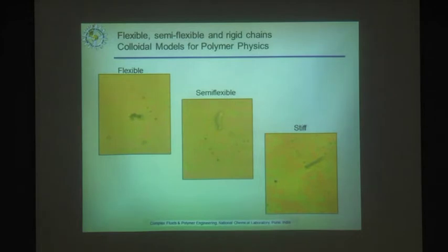The other thing that is kind of fun and exciting for us is the fact that if I decrease the number of particles that I put in here, instead of making a 3-dimensionally cross-linked structure, I can make essentially colloidal strands. We can make them by changing the degree of cross-linking. You can either make them highly flexible. So this is actually composed of about 20 particles that form this very flexible polymeric strand. And you can see that over time, this thing will unfold to form the large length scale structure. So essentially, it's a mimic of a polymer chain.